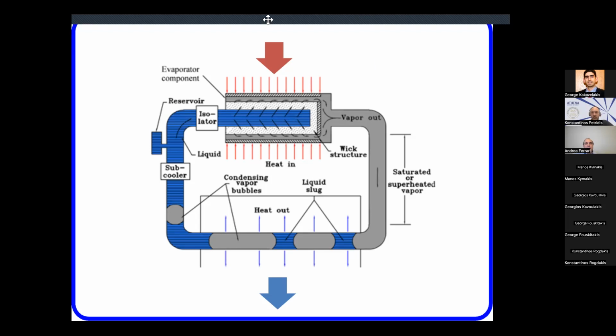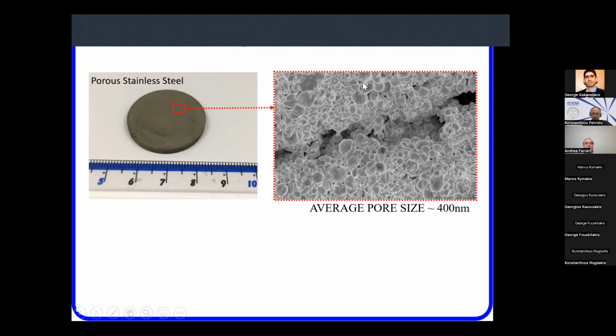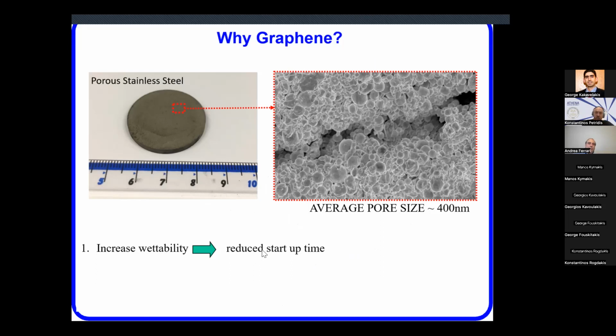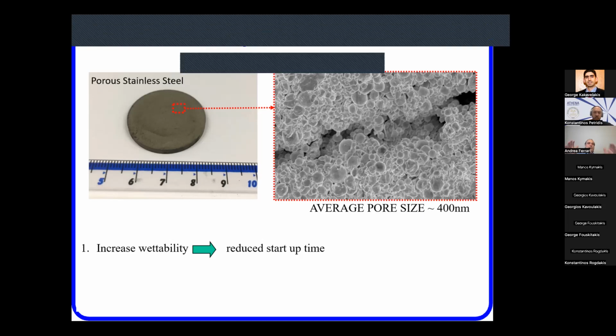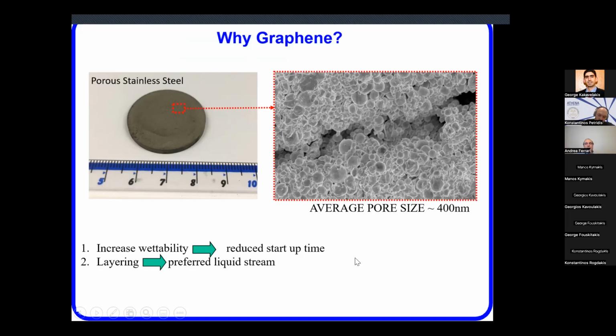So this is a very interesting application, and we have worked on it for a while, and we are still working on it with Leonardo. But the use of graphene increases the wettability, so reduces the startup time, because these pumps, because they don't have any mechanical parts, don't have a switch to be turned on and off. They turn on automatically when one side is hot and one side is cold. And so you need to make sure that they actually function immediately. And there's been several problems in satellites where they were down for months at a time because they were not working. So the increased wettability really reduces startup time.